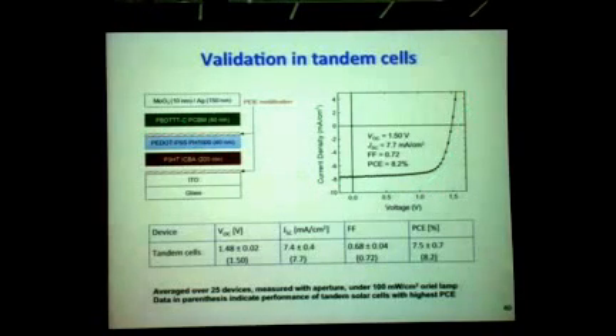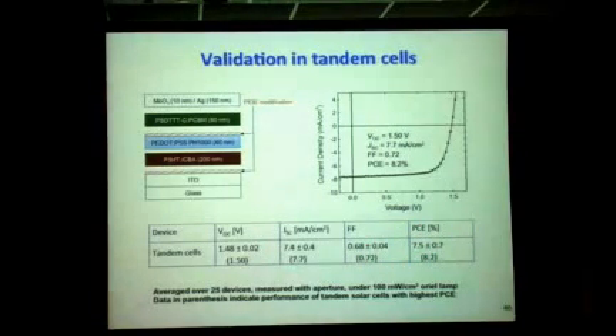So here you can see this is our champion cell. It has a power conversion efficiency of 8.2%. What's also very nice is that we have fill factors here that are larger than 70%, and actually larger than the individual fill factors you can get in these cells if you make single junction cells with some of these materials. We fabricated many of such devices, and if you look at the average values over 25 devices, we still get fill factors close to 70% and efficiencies in the range of 7 to 8%.